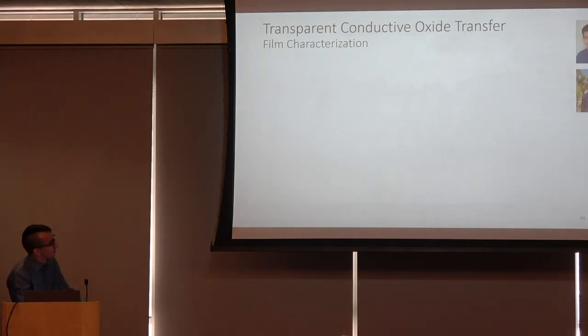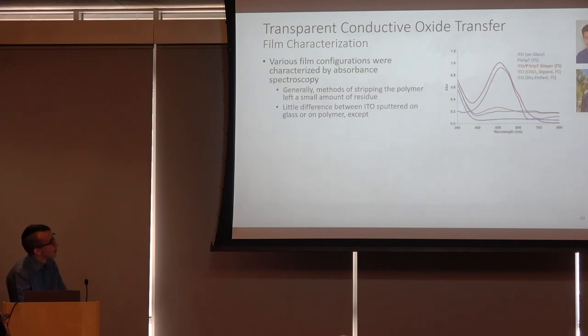With the help of Ben and Jaden, we did some film characterization, starting with absorbance spectroscopy. We prepared either ITO sputtered directly on glass, freestanding P3HT, ITO P3HT bilayer, or just freestanding ITO with the polymer having been stripped either by chloroform dipping or by just air plasma etching. And so there's a variety of features here, but I want to focus on the blue here, which is the ITO on glass, and then the stripped scans, which are these two.